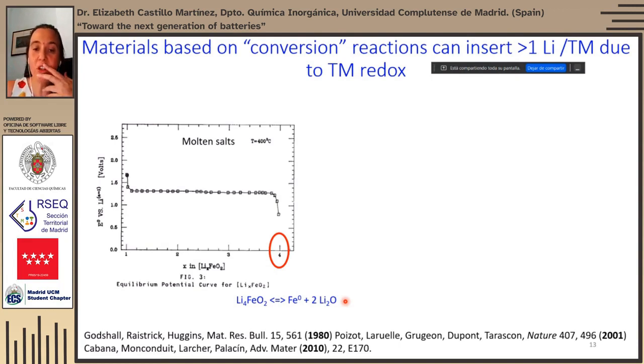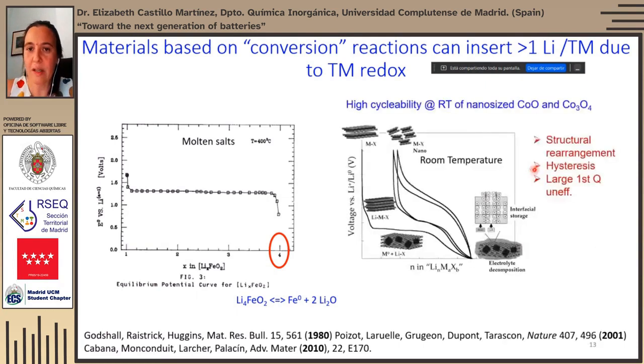So although this type of reaction was known from the 80s, and was reported for many oxides, nitrides, and sulfides, it was not until 2001 that high cyclability was reported at room temperature for nanosized cobalt oxide, in both the rock salt and the spinel crystalline structure. And what is found in the room temperature cyclability is that the first discharge plateau is quite different from the following cycles.